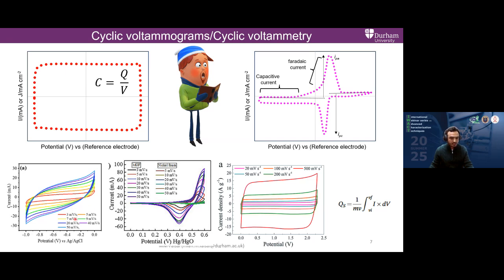So you can easily get capacitance as a function of the scan rate, capability as a function of the scan rates, from the real application of the electrode material. The second graph actually shows you again the 3 electrode assembly, in which the potential is recorded as a function of Hg/HgO reference electrode, and the material is tested at different scan rates, and then you can play with the parameters and analyze accordingly.